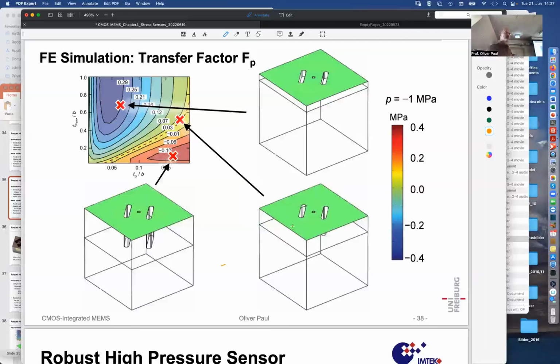And if you go somewhere in between, you can be sure enough to obtain a zero response, because the contraction under the subjacent glass body and the bending due to the contraction of the glass body will just compensate. Effectively on the surface, nothing will then happen. And then you think you build your super duper sensor and it outputs zero as a function of pressure. Bad luck. Well, bad design actually. And so that's why these optimization studies are important.